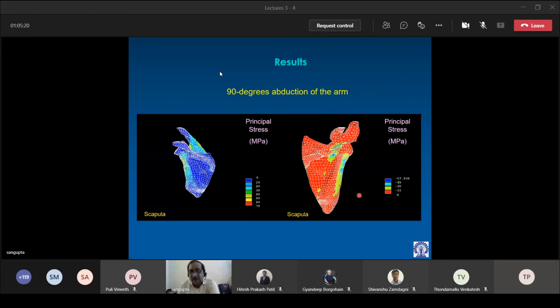Okay, so we had actually quantified the stress distribution, and we could see that the thick bony ridges are the regions where a lot of huge load transfer happens, and in the thin part, the fossa area, the stresses are very less. So this actually answers some important questions related to structure and function. Okay, so the thick bony ridges in the scapula are responsible for load transfer, whereas the thin bony parts act more as muscle attachment sites.